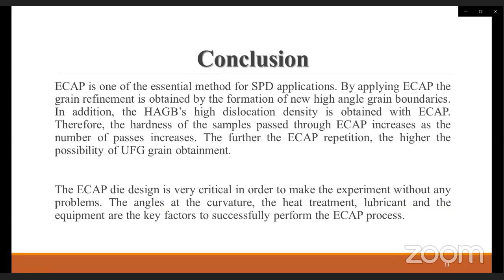In the conclusion, the ECAP is one of the essential methods for SPD applications. By applying ECAP, the grain refinement is obtained by the formation of new high-angle grain boundaries. In addition to the high-angle grain boundaries, high dislocation density is obtained with ECAP. Therefore, the hardness of the samples passed through ECAP increases as the number of passes increases. The further the ECAP repetition, the higher the possibility of ultrafine grain obtainment.